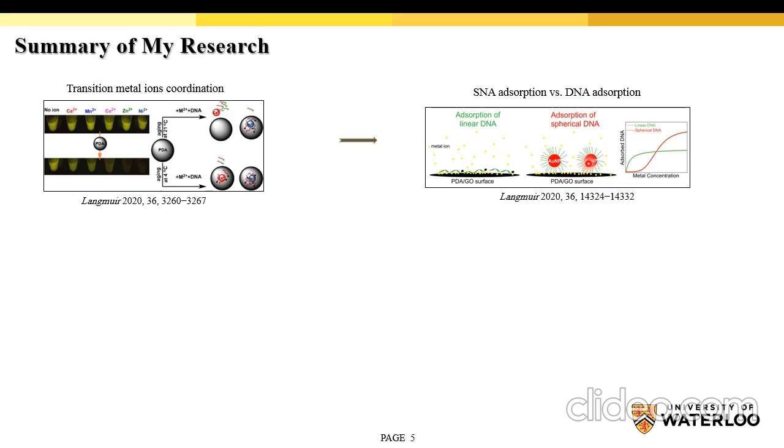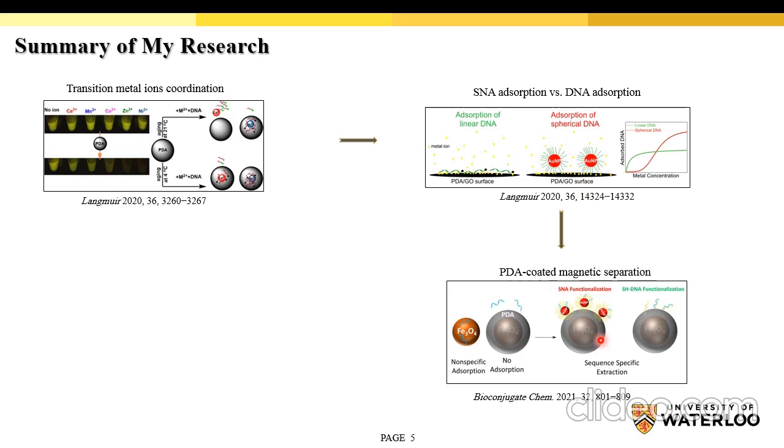That stable absorption was also used where a magnetic nanoparticle system was coated with PDA and decorated with spherical DNA. And then, highly sequence-specific DNA detection and extraction was achieved by that system.